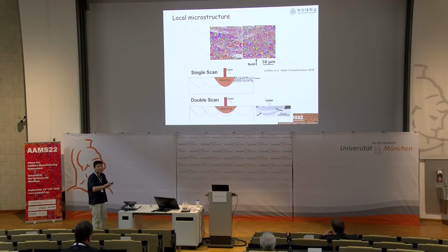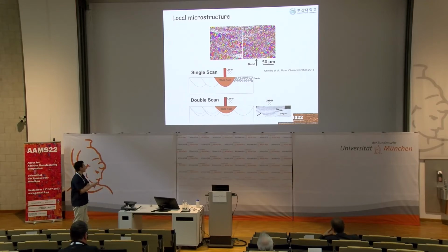this work has been published quite recently, and we suspect that this was due to the different heat flow that influences the solidification rate, because when we first scan the laser, one side is always the porous powder layer, which has less thermal conductivity, and if we scan the laser twice, which is the case of the laser contour scanning, then our melt pool is always surrounded by the already consolidated solid, so probably the cooling rate or the solidification rate is slightly higher.